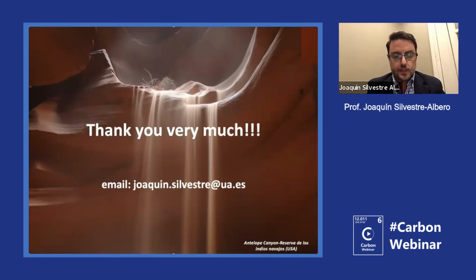I mean, the point is that when you do the extraction of these natural crystals, at the end, you need to break the ice network. And the best way to do it is either decreasing the pressure in the surrounding of the gas hydrates or warming them. But in any case, you will finish with liquid water. And that's why, as the density is different, you will have a collapse of the ground. So that's why the in-situ replacement can be a very good option if you are able to keep the hydrates, instead of having methane inside the cavity, replacing it by CO2. Because that means that you will be able to keep the hydrates, and you only are replacing the molecule that is in the middle of the cavities.